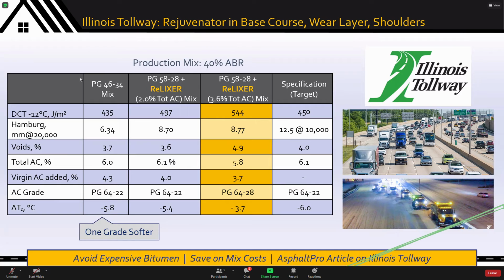And you can see that the DCT properties, the fracture toughness properties, they were using DCT as their measure of fracture toughness. They were using Hamburg wheel rutting as a measure of their rutting resistance. As you can see, the ReLIXER samples, this is 2% of ReLIXER to a normal grade bitumen, not a softer grade, normal grade bitumen, certainly brought the material in line with specs. They were certainly impressed enough with this that they wanted us to try and make a slightly higher dosage so that they could try and improve upon the cracking spec parameter.